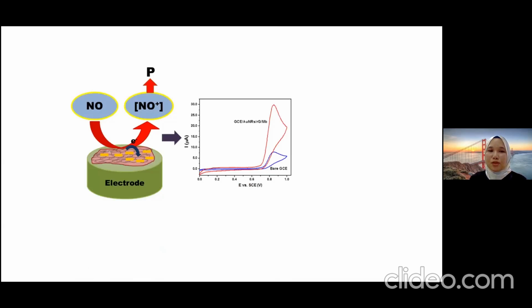Okay, so it is well known that sodium nitrite can serve as a source of nitric oxide in an acidic solution, with pH less than 4. So it will undergo a disproportionation reaction to produce nitric oxide, and with the addition of sodium nitrite in the bulk electrolyte, we can generate a series of nitric oxide concentrations. So here is the cyclic voltammetry, and you can see that compared with the bare GCE, the nanohybrid shows a higher current for detection of nitric oxide.